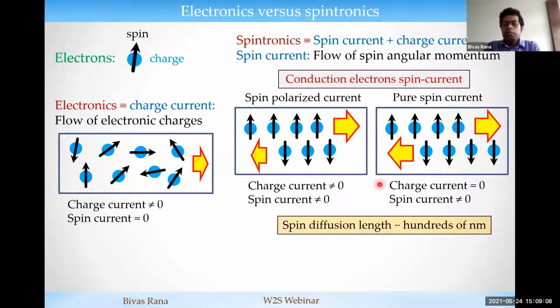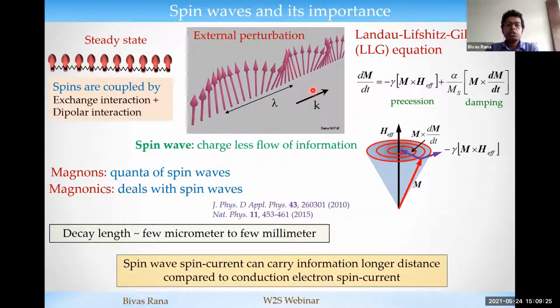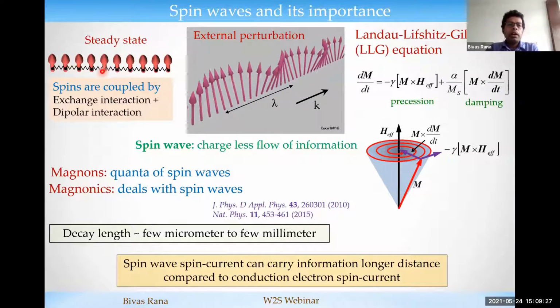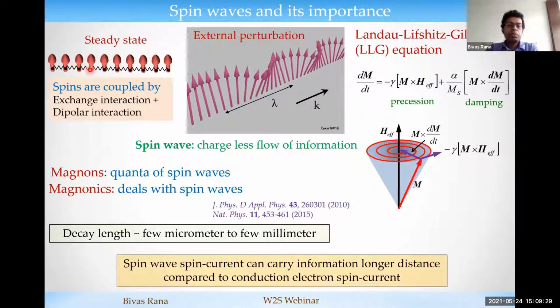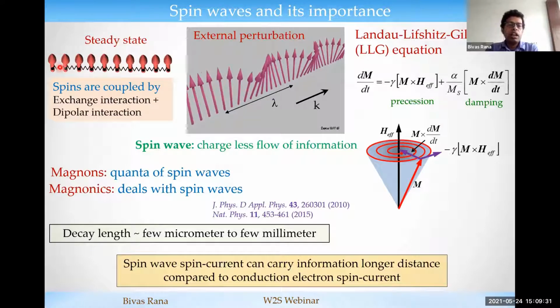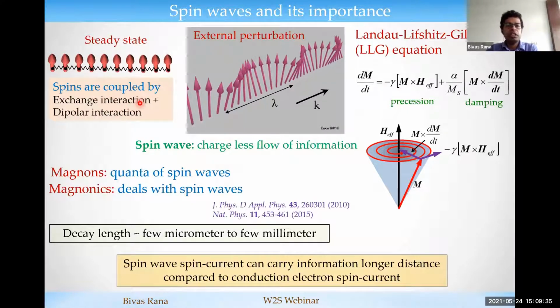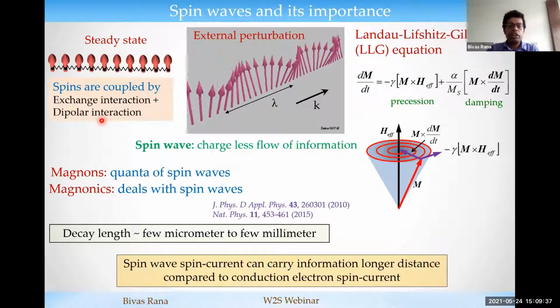But the spin diffusion length of this conduction electron spin current is limited to hundreds of nanometers in a clean metallic system. So what is the other type of spin current? That is called the spin wave. In the steady state, the spins in a ferromagnetic material are aligned like this, because they are coupled by very short range exchange interaction and long range dipolar interaction.